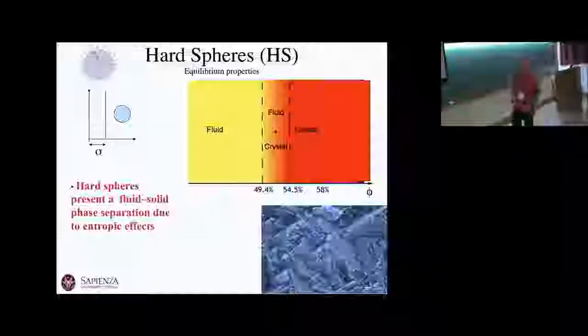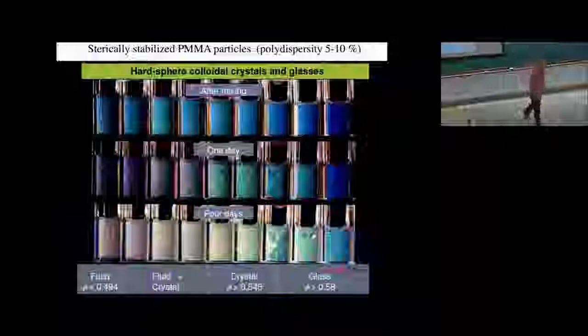The experiment showed that hard spheres do crystallize. Even a particle with nothing but a hard-core excluded-volume interaction — which you can realize experimentally by coating a colloidal particle with very tiny polymer brushes to prevent van der Waals attraction — forms a beautiful FCC crystal visible in microscopy images. There is no doubt that hard spheres crystallize, driven purely by entropic effects.